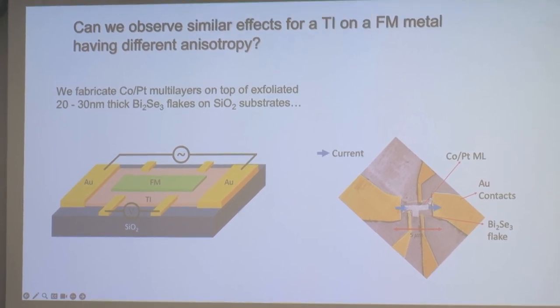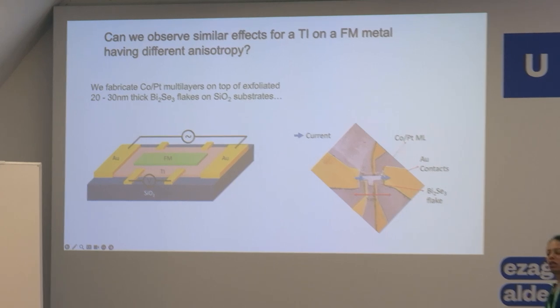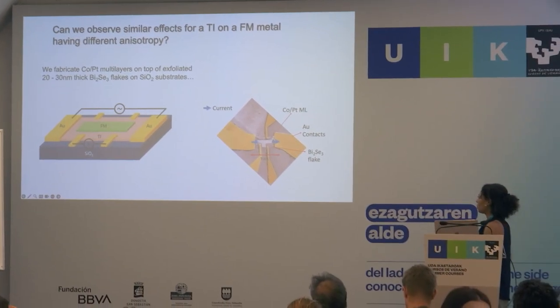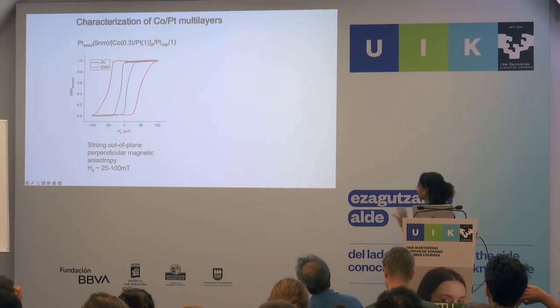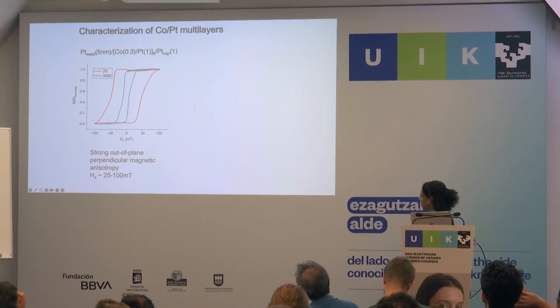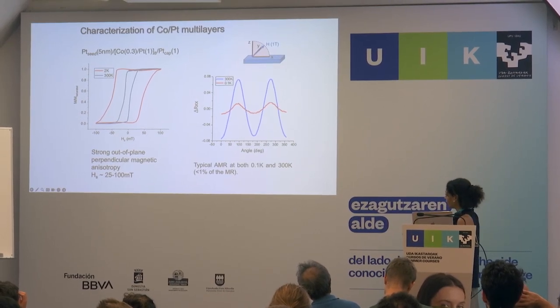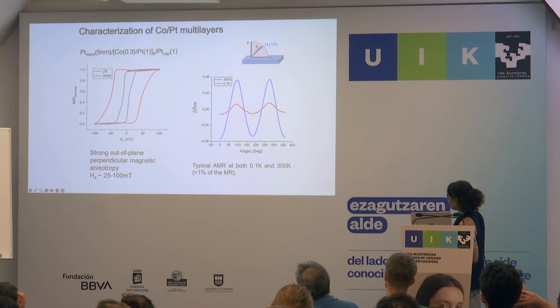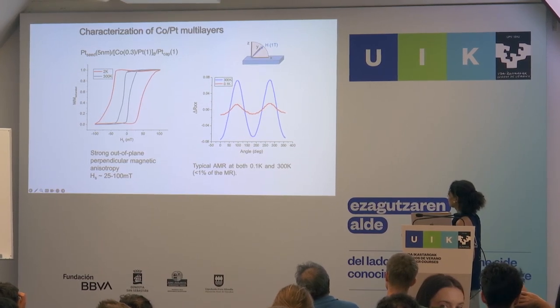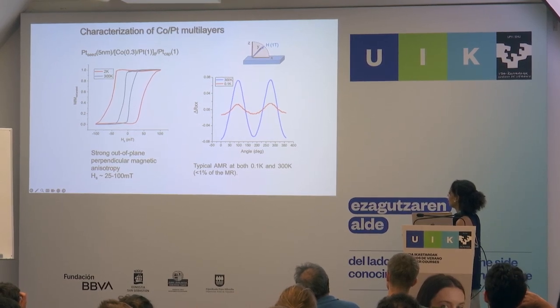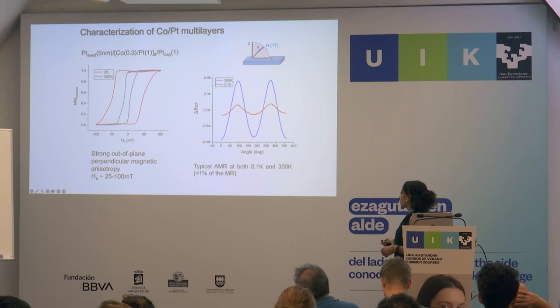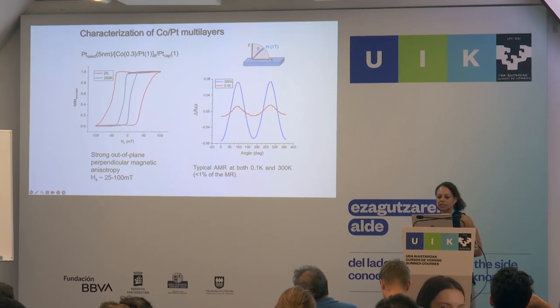And cobalt platinum multilayers have an out-of-plane magnetization, which is why we use these to see what happens when we couple these materials. And again, in this case, we can see this strong out-of-plane perpendicular magnetic anisotropy of the cobalt platinum. And you can see the typical AMR of the cobalt platinum. The scale here is something like 0.08% at room temperature and then much lower at low temperatures. So it's usually less than 1% of the magnetoresistance.